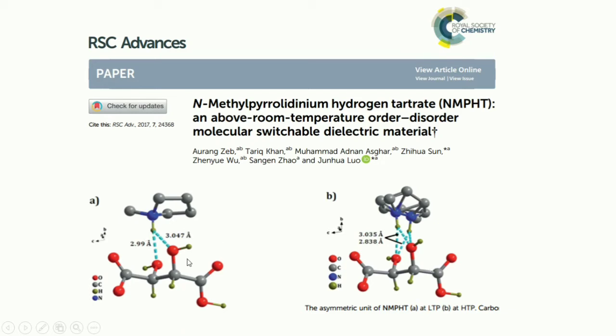The molecules are the same in the low temperature phase and high temperature phase, but if you observe more closely, you can find quite a large difference between the two structures, because here we can say this nitrogen is actually delocalized over two spaces, here and here. We can say this is actually a disordered state of the hydrogen.